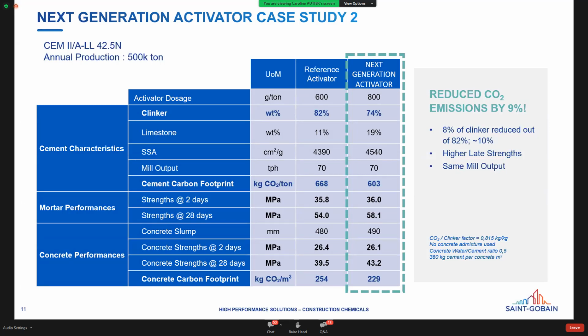This benefit is also maintained at the concrete level, where the 2-day strength was still maintained, and the 4 MPa gain at the mortar level was also observed at the concrete level. We are very proud of this case study, as the use of the next generation activator has allowed to decrease the CO2 emission by 9% at the cement and the concrete carbon footprint.